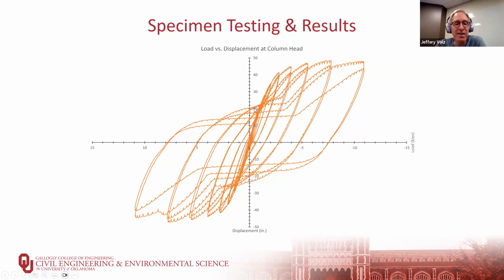So initially, linear elastic, just like the RC column, just like the SCC column. Eventually, we start getting some inelastic response. We start to yield part of the steel tubes at the extreme fiber, but we're still increasing load. Additional cycles, we're still increasing load. We get up to about 49 kips. So we've got an almost 14% increase over the SCC column with the UHPC, which is more than statistically significant. So it's a noticeable increase. And we have a bit more area under our load deflection response, more energy absorption.